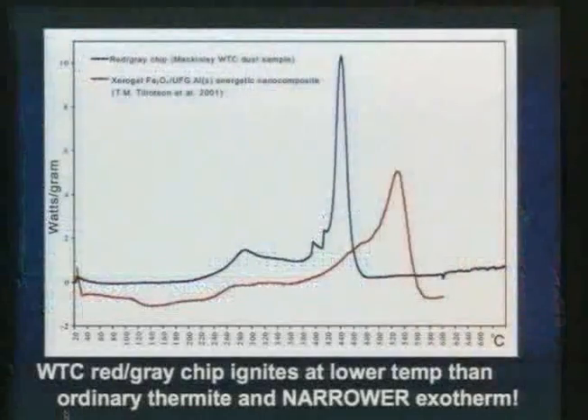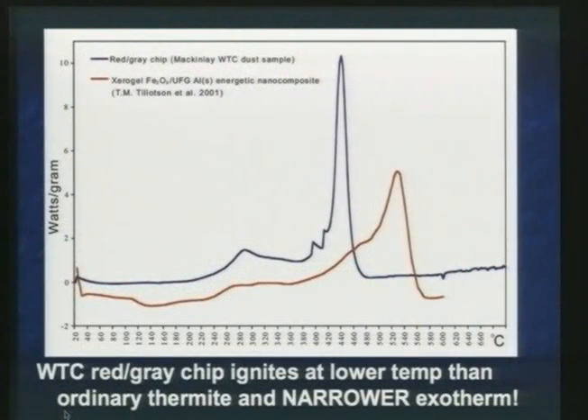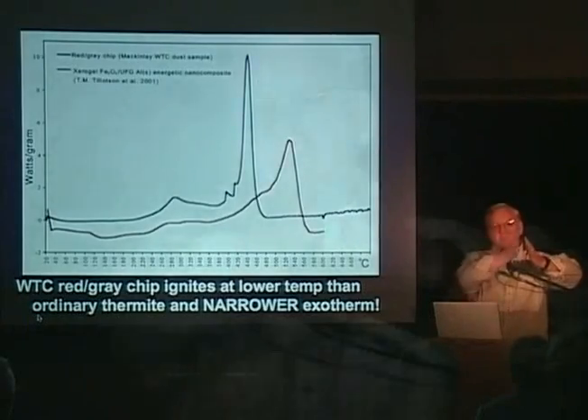The red chip, from the red material from the World Trade Center dust, I can't remember. Yes, it says McKinley. This is a McKinley sample, Jeanette. And look at that, very narrow, and goes off at about 430 centigrade. A little lower in temperature. The finer the material in general, the lower the temperature at which it ignites. The narrower the peak, the more explosive, you see, the faster the energy release.